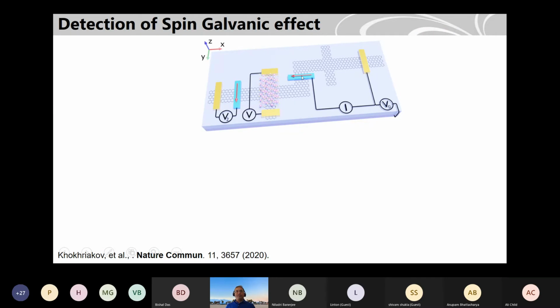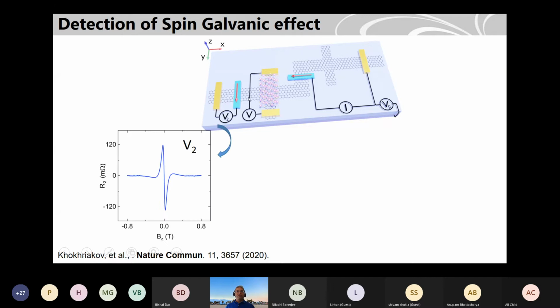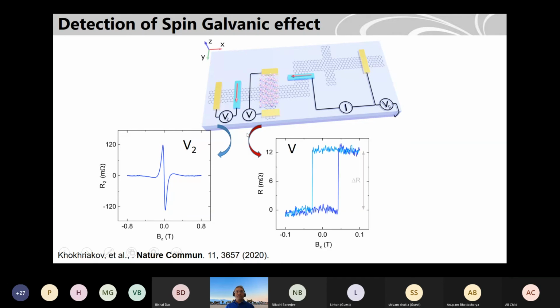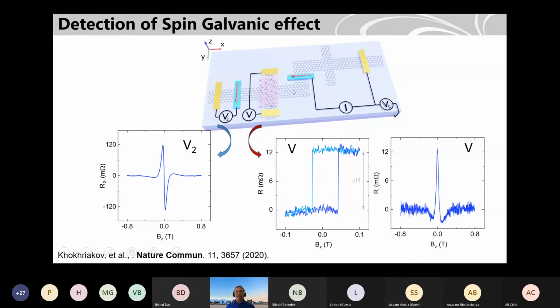We send a spin current from this graphene-on-ferromagnet contact here. The spin is coming, and we should be able to detect a voltage with this ferromagnet, and at the same time detect a voltage across this heterostructure. When we detect this voltage V2, because this ferromagnet and this ferromagnet are not collinear, they are at an angle of 90 degrees, we get these Hanle curves, which are asymmetric. When we measure the voltage V with an in-plane sweep, so when we switch this magnet, we actually see this change in voltage that we measure here. And when we apply a perpendicular field, we also see that spins are coming and precessing in the channel, and the voltage signal is also modulated like this. So this confirms observation of both spin valves, and Hanle confirms that it is coming from the spin.